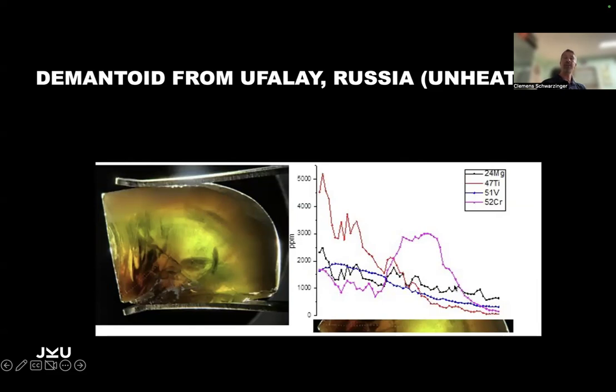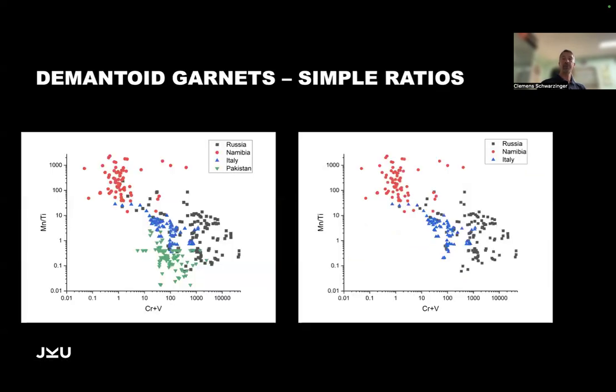So with this, you can identify the source of color in your gems, but you can even go a step further. You do, like I told you, a chemical mapping of all the elements. This was at the very beginning when I was starting with working with things like this. So we were just monitoring 7 different elements. And then we tried different combinations like the sum of chromium and vanadium versus the ratio of manganese and titanium. And then we tried to identify if it is possible from a scientific basis to differentiate demantoid garnets from, for example, Russia, Namibia, or Italy.